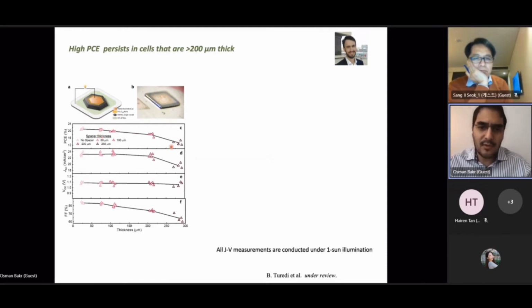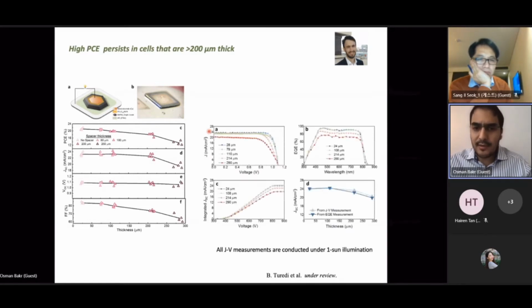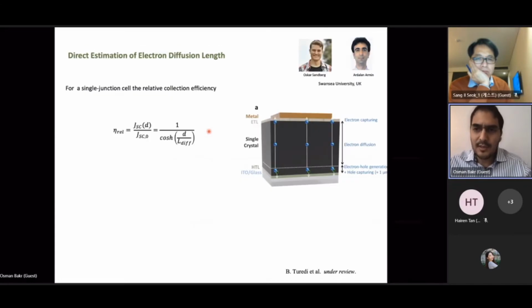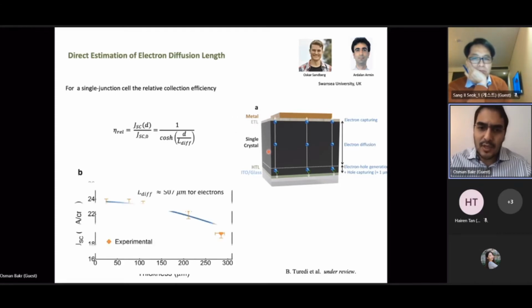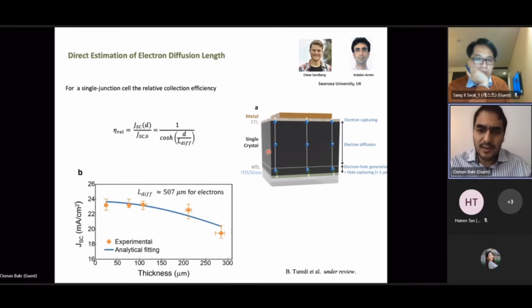And so you'll see that the power conversion efficiency only starts really dropping quite substantially when you start going above 200 microns. And so then what you could do is you could look at these current trends. Working with our collaborators from the University of Swansea, they developed an analytical model to estimate the electron diffusion length based on the trends we see in the short circuit current densities versus thickness. And what we found is that if you fit this model to our solar cells and the short circuit current density as a function of thickness, the diffusion length of electrons in the device actually exceeds 500 microns.